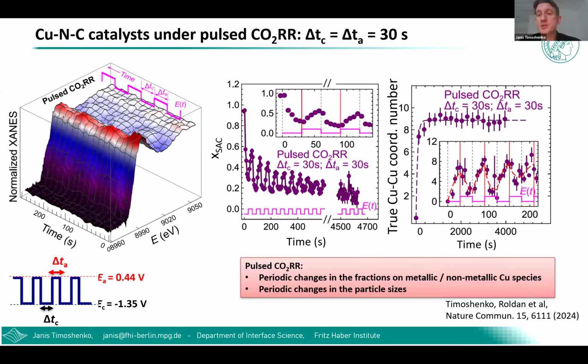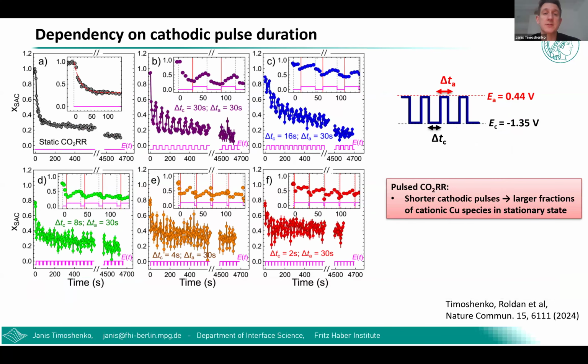Now, depending on the duration of applied pulses, we can easily steer the system, in the sense that the amount of cationic copper which remains in your cluster, in your system, depends strongly on the duration of applied pulses. So in this figure, we compare 6 different experiments where we did measurements under static applied negative potential and under pulse reaction conditions with 30-second durations for negative and positive potential pulses, with 16-second negative pulse and keeping the positive pulse again at 30 seconds, and so on. So 8 seconds, 30 seconds, 4 seconds, 30 seconds, and 2 seconds, 30 seconds pulse combination. And in each of these cases, you can see very nicely that this average copper oxidation state changes quite systematically with the duration of applied potential pulse.